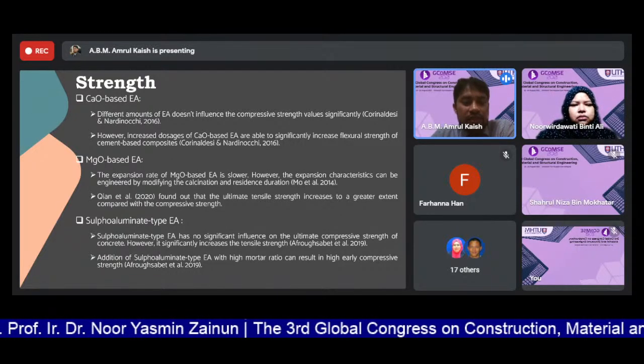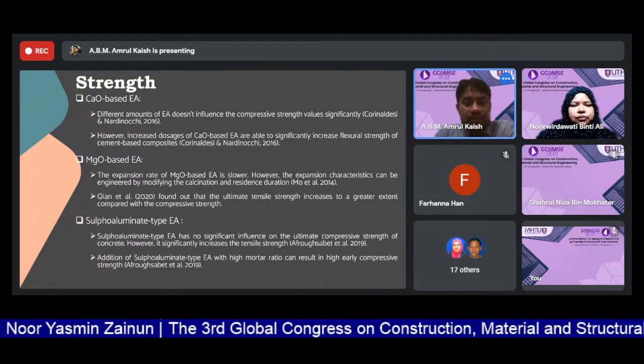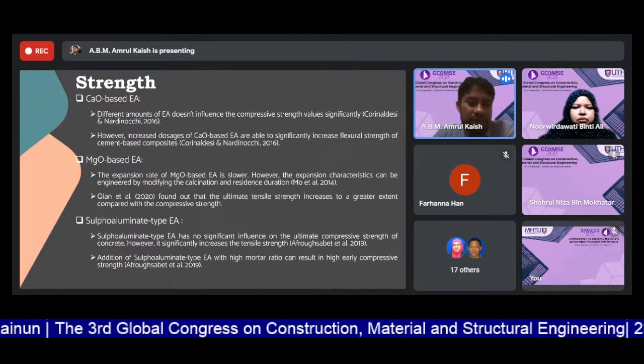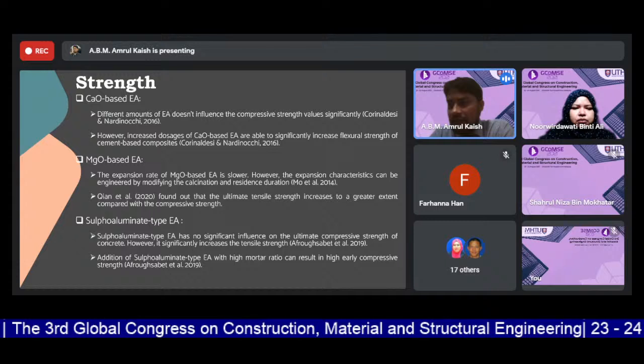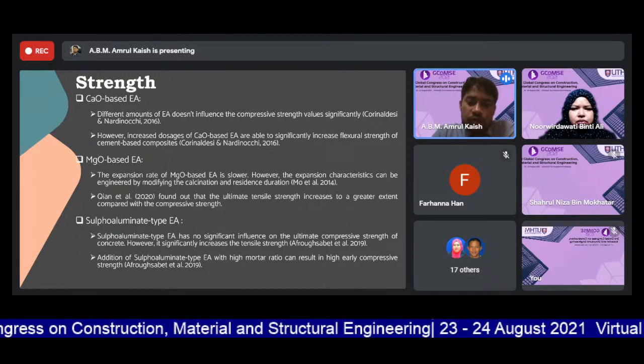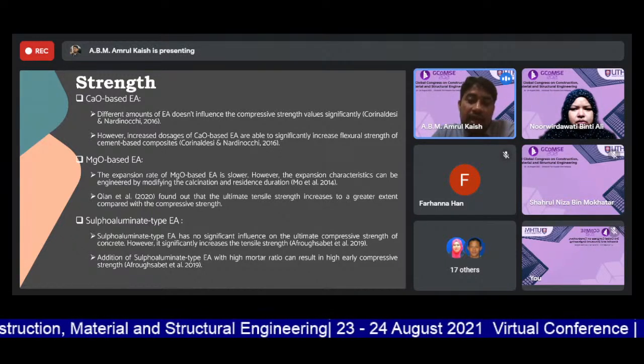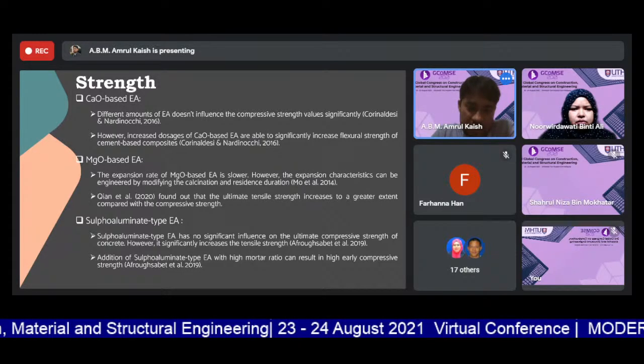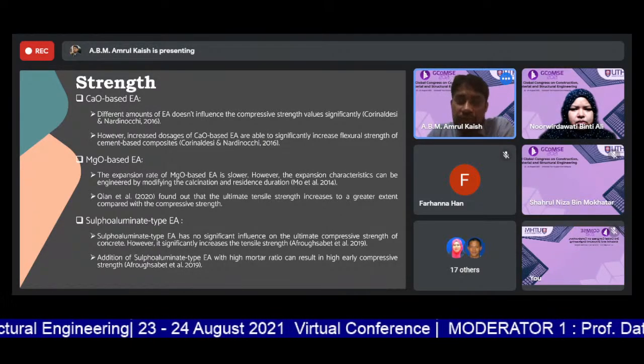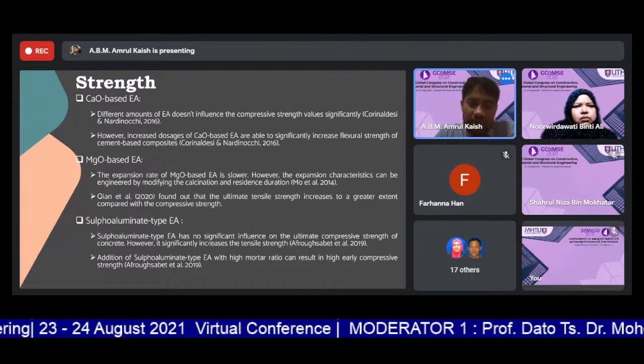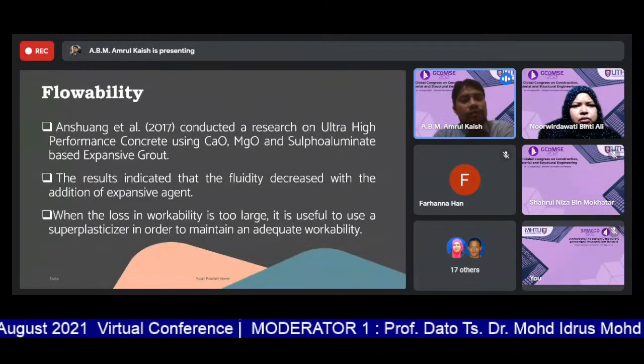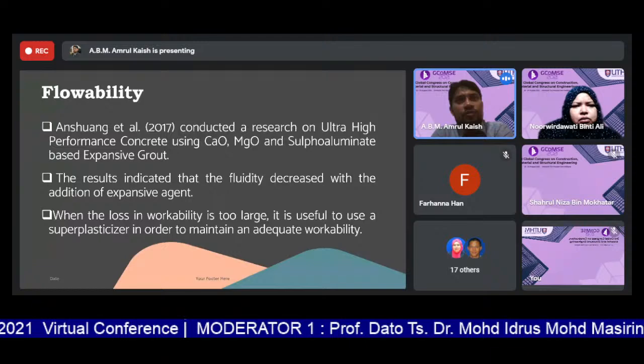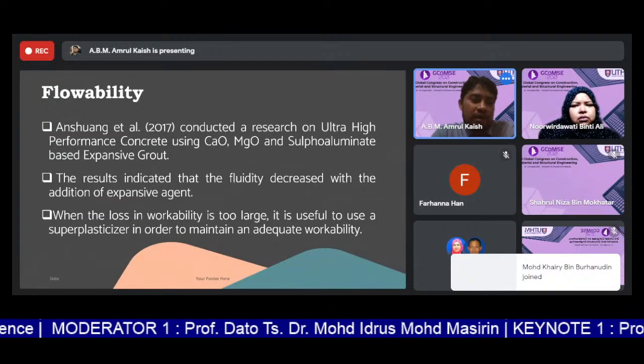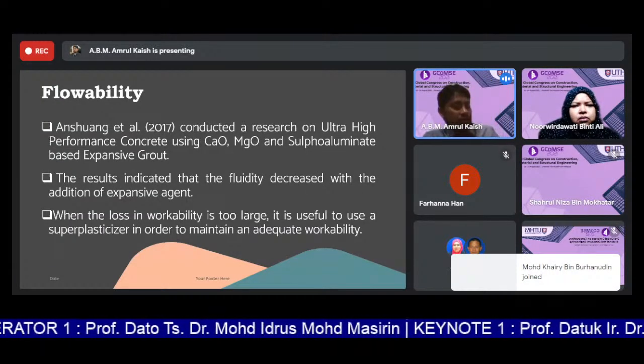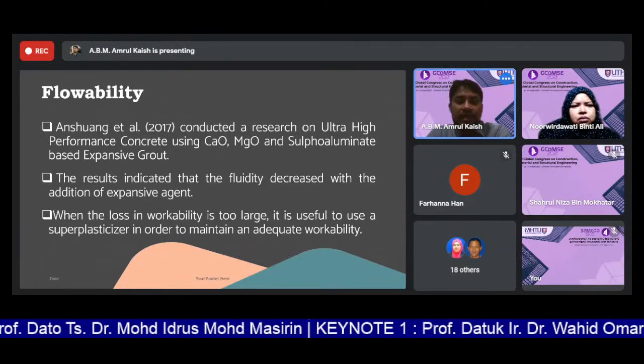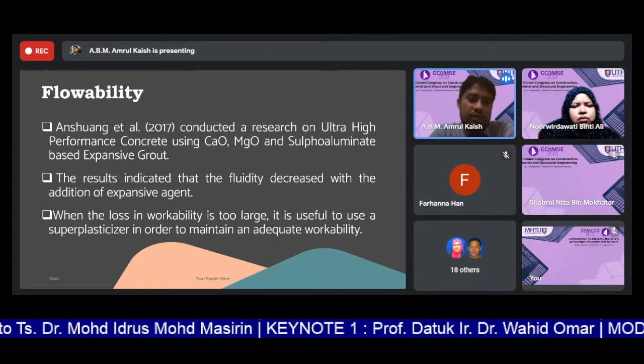Okay, then the sulfoaluminate based EA, this one has no significant influence on the ultimate compressive strength, but it has a significant effect on the tensile strength, and it also results in a high early compressive strength if we use it with a high mortar ratio in the cementitious composites. Then with the flowability, all these three types of expansive agent have an impact on the flowability.